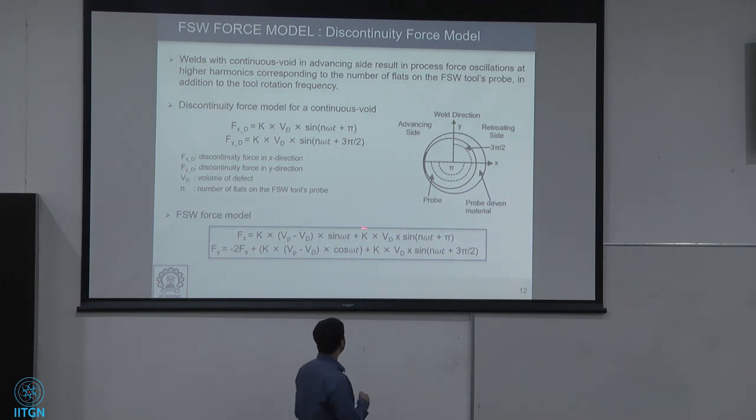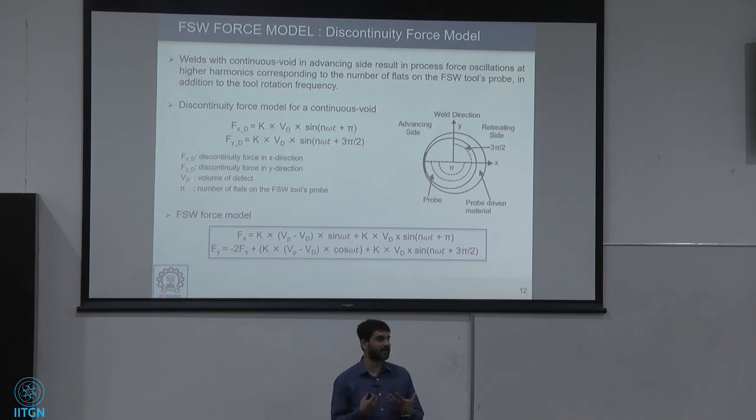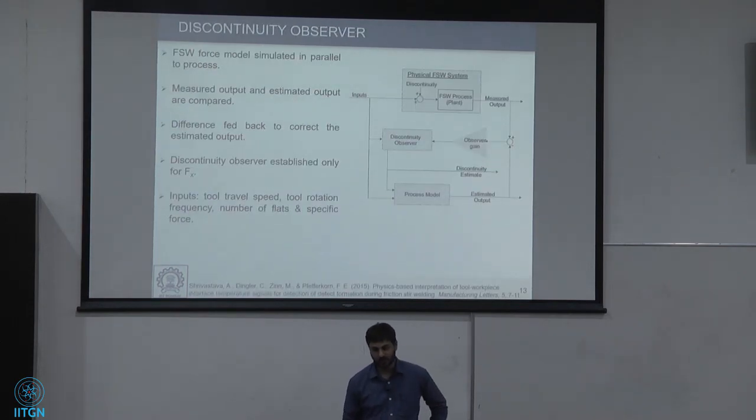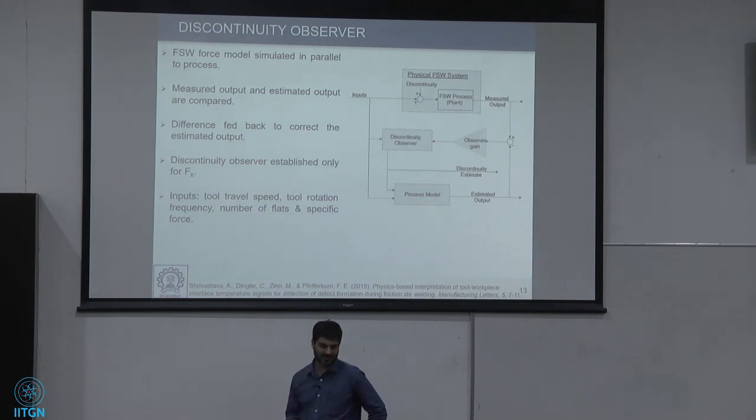That gives us a complete model for which the only constant is k. Vp can be calculated theoretically, the way I mentioned before. Vd is going to be the outcome, given that forces are measured or known in this model. So a discontinuity observer was established.